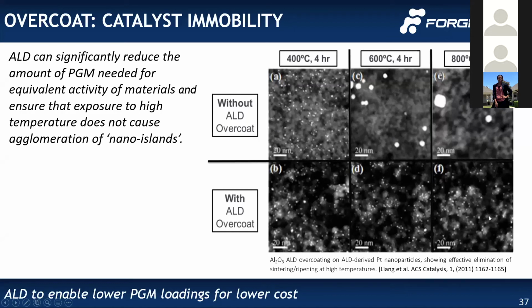So you can stabilize your platinum by having an overcoat. This allows you to reduce the amount needed, because over time, if you operate at 600 degrees Celsius, you have to have more platinum to have the same activity at end of life than you would if you have an overcoat on the material.